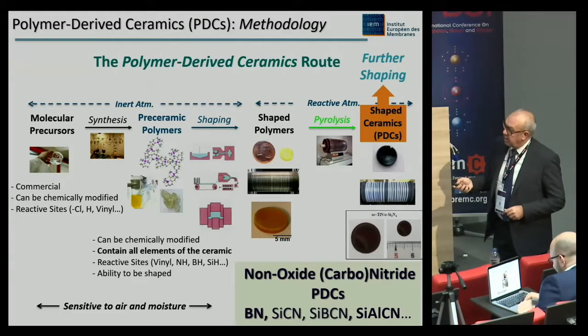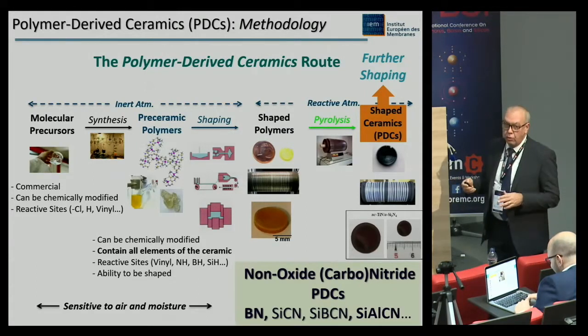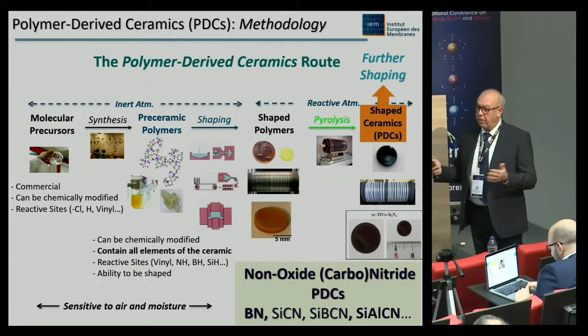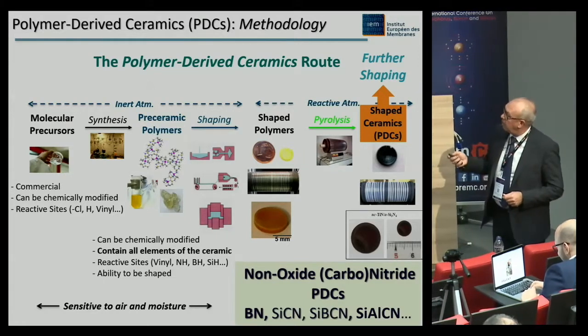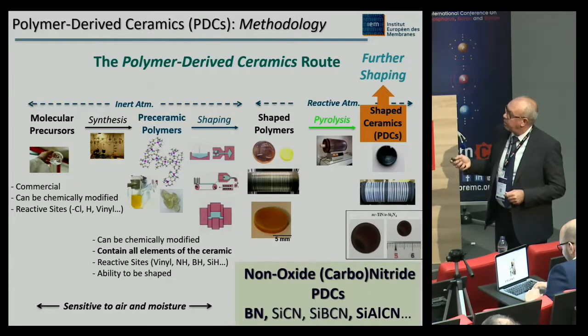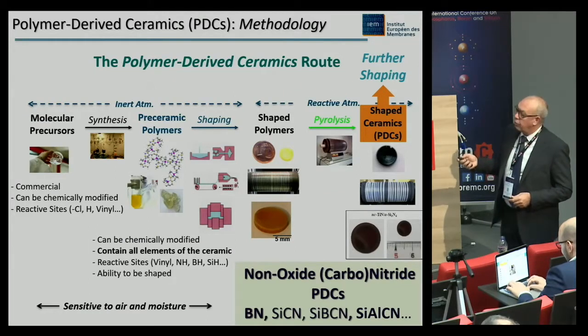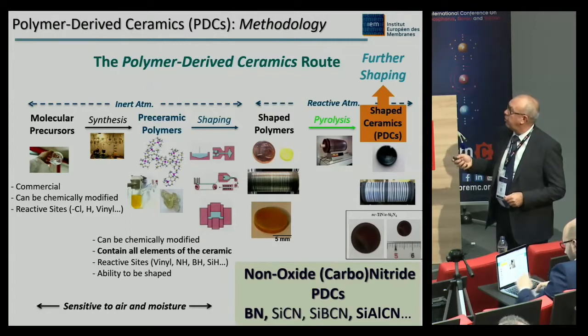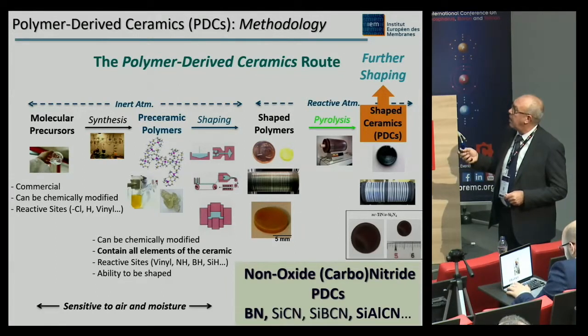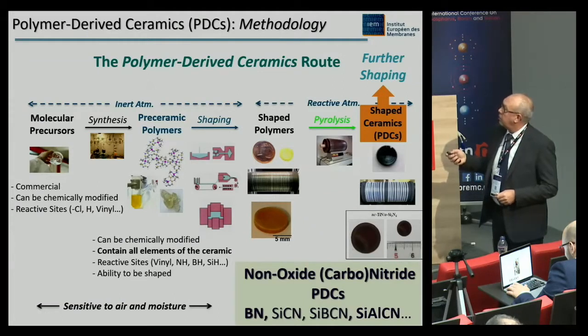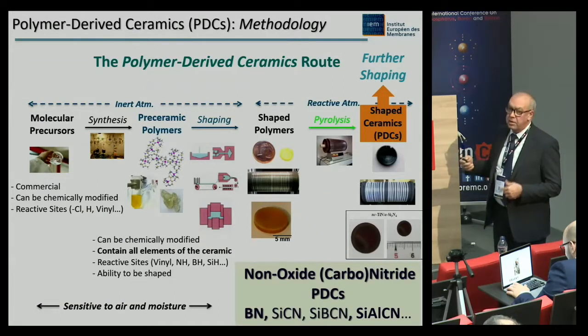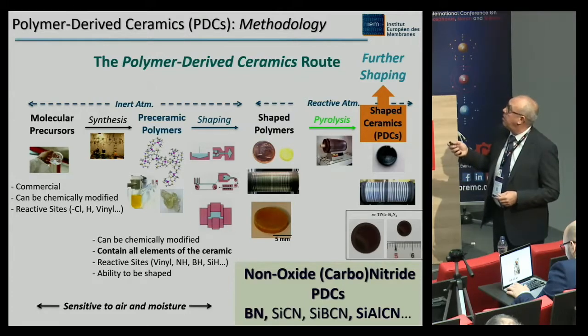They also display an ability to be shaped, and for this you can use methods derived from the plastic industry, for example. You prepare the shaped polymer by, for example, the spinning method or plastic shaping and so on. And after that, you have to treat your polymer at high temperature to convert it into an amorphous ceramic and finally a crystalline ceramic. So these ceramics at this stage can also be powders, and they can be shaped in another way after that. In this way, it's possible to produce non-oxide ceramics, particularly boron nitride.